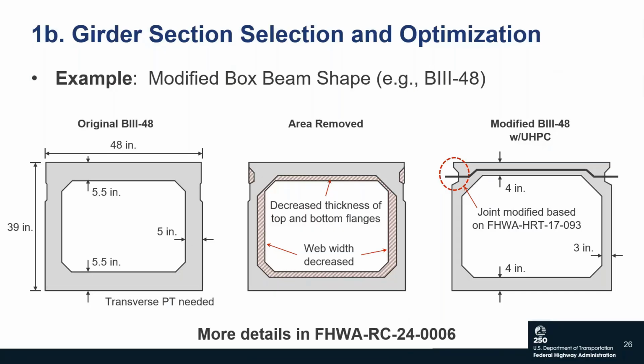I guess a lot of the time when you're using the UHPC as your riding surface, you're going to grind off the top quarter inch or so. So this would be planned into the casting of the beams and the casting of the joints, and that would help you to achieve the desired profile within your necessary tolerances.